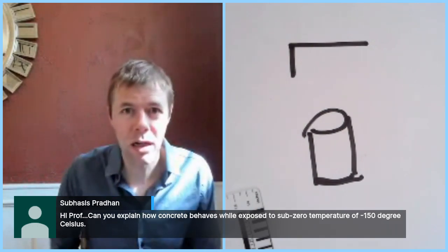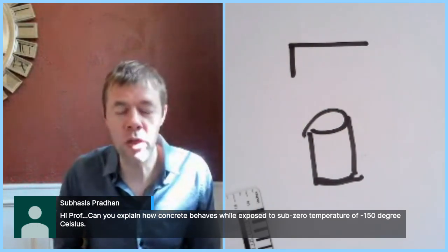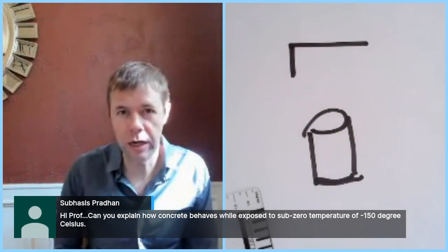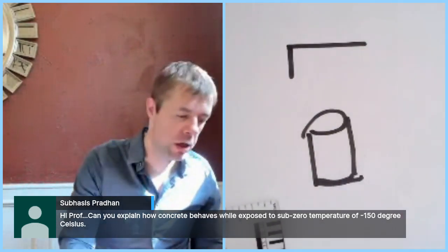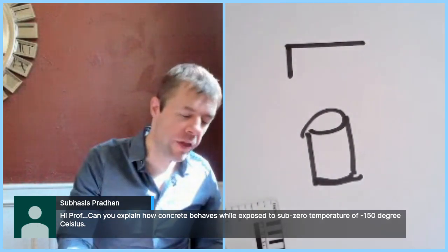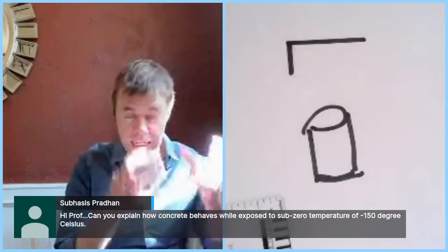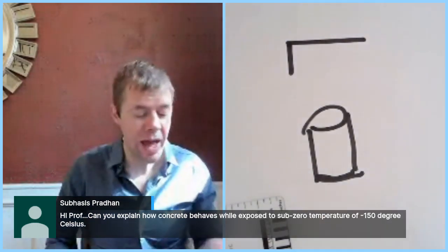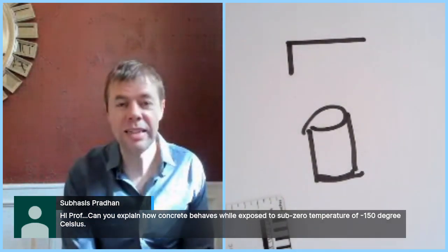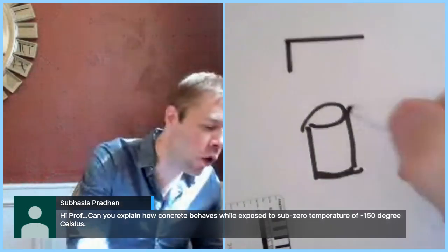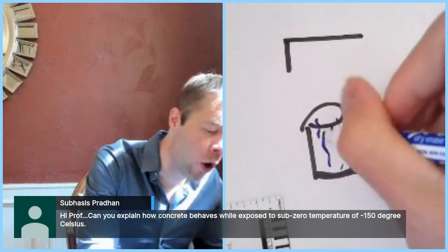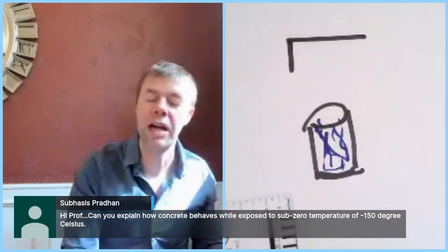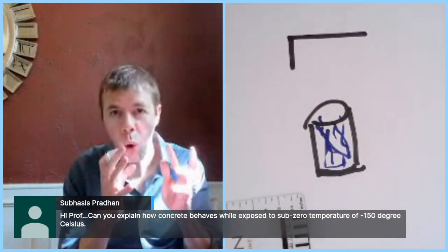And you said, what? Why would they do that? Wouldn't that damage it? Wouldn't that hurt it? I mean, because it wasn't air-entrained concrete. Wouldn't that do something to it? Well, what they did is they took it to a very, very cold temperature, and the ice formed inside of it. Ice crystals all formed inside of it. And they actually tested it cold. They tested it frozen. And all those ice crystals inside of it all aligned and all made an inner structure inside of the concrete to hold it together.